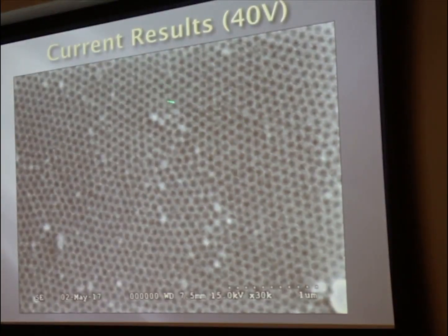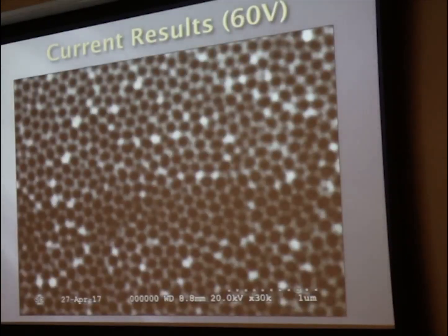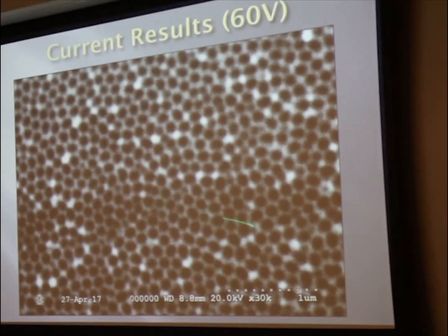And you can tell there's hexagonal ordering because if you focus on one pore there, you can see there's 6 of them hexagonally structured around. You can look around here. Pretty much no matter where you go, except for at these little deformities in the surface that would take further optimization to get rid of, you can look at one pore and see there's a hexagonal structure to them. It looks pretty nice.